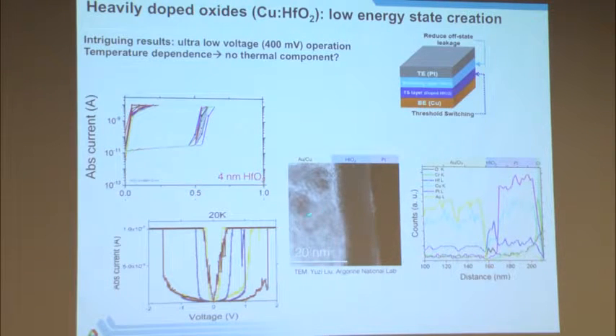If we do a TEM analysis on it again, clearly there is a lot of copper in the hafnium oxide, and so that is indeed modulating the conductivity. But a lot of this behavior is not understood at this time, and we are trying to figure this out, but the promise remains that it can have low voltage operation.